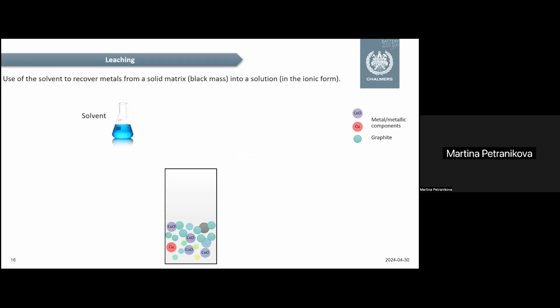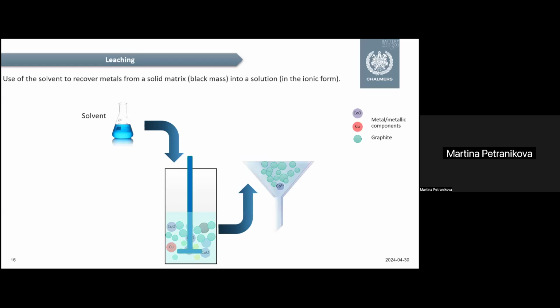The leaching is that we have our black mass, which in this simple form, we can consider that we have some transition metal oxides, we have maybe some copper from the foil, and then we use the acid. We apply some time and also some temperature, we mix it for some time, and then what we get is that we dissolve these metals into the solution, and we call it that we get them in the ionic form. And then we apply filtration or the separation.